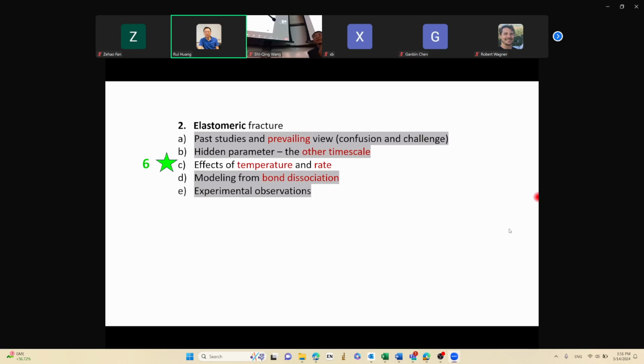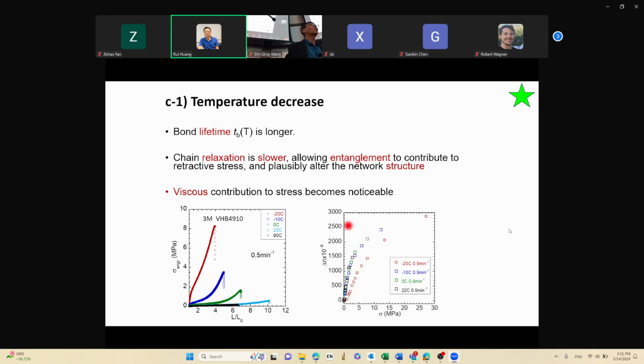So let me go to the dear question that we all had, the temperature and rate effect. Let me go through it very slowly. What does it do when you lower temperature? Three things happen. The bond lifetime is longer because there's less energy available to hop over the barrier. Second, relaxation is slower. If you fix the same rate, you end up effectively being able to stretch much more efficiently. Third, if you go toward glass transition, indeed you pick up a viscous stress. But I will show you that's nowhere near where we need to be to have the story understood.